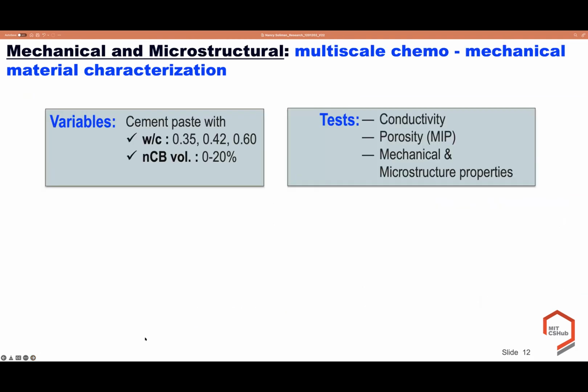Moving now to the third question about the effect of nanocarbon black on mechanical and microstructural properties, using the multi-scale engineering approach that we developed here at MIT. And here we use different water-cement ratios going from 0.35 to 0.6 and different nanocarbon black volume fractions from 0 to 20. And we measure the conductivity, porosity, and the mechanical and microstructural properties.